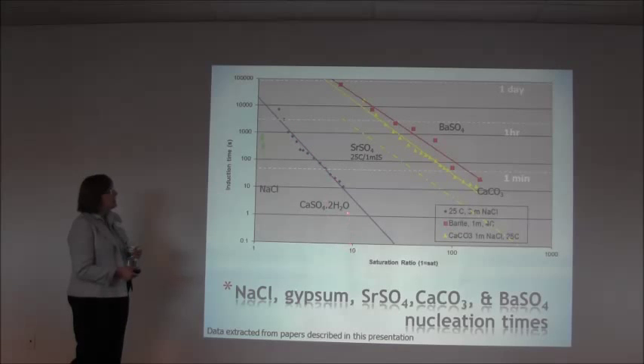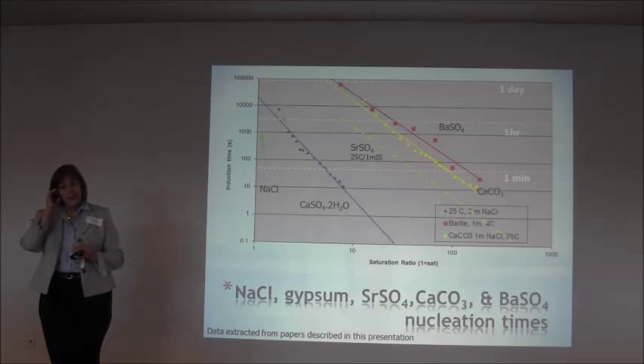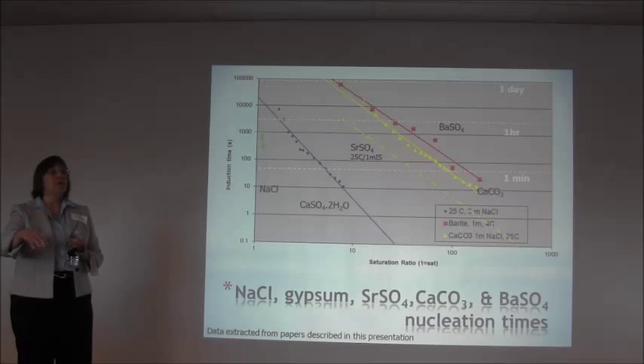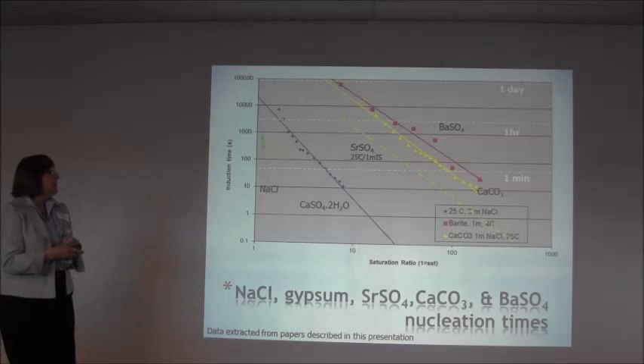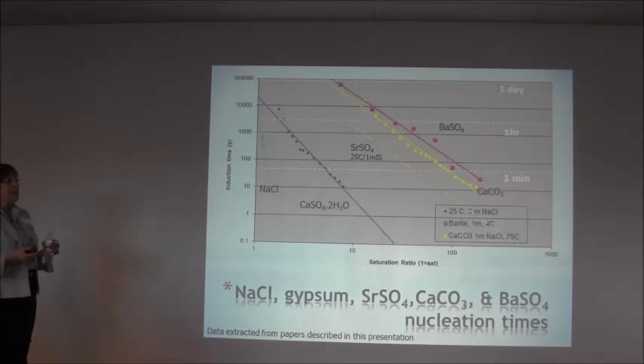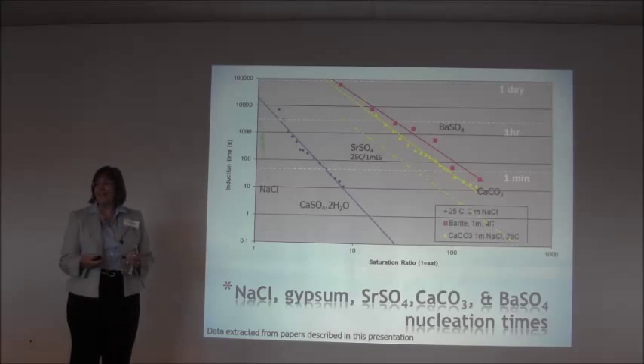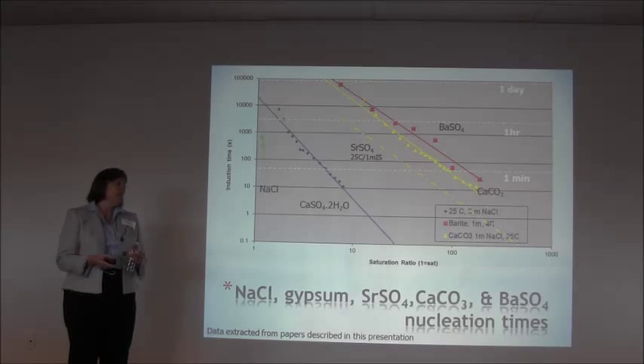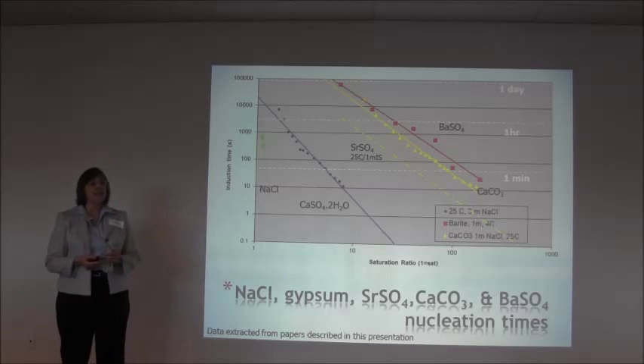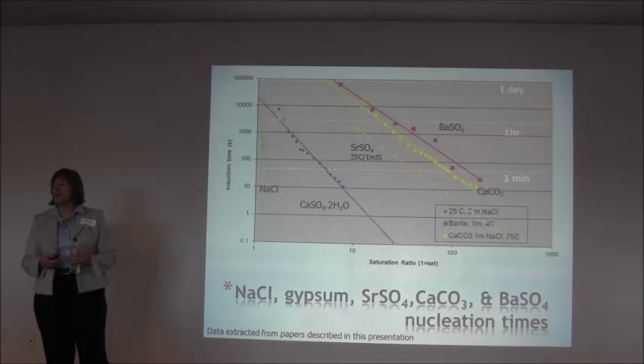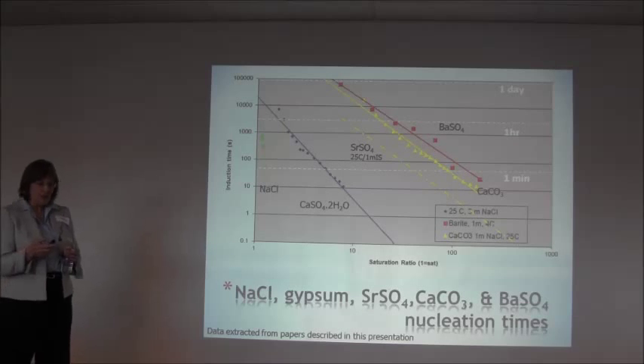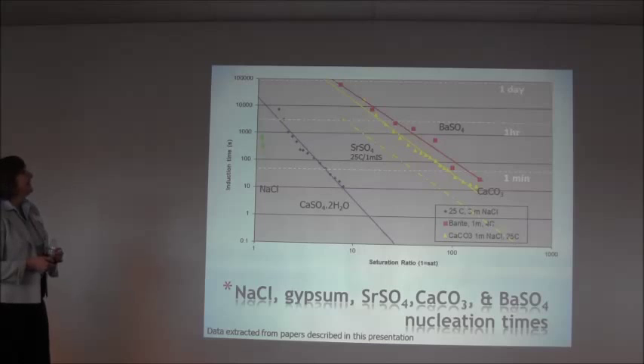So that means that your scale tendency on gypsum, for example, can be much higher. It can be up at 10 if your induction time, the time in seconds, is only going to be 10 seconds. What that means is if you have something flowing really quickly, it's not going to have time to nucleate and adhere. So even though we're worried only about the thermodynamic driving force, you can see that there's different ways that you can calculate. Okay, even though the program said the scaling tendency is 4, is that a problem? Well, no, it's not going to be a problem. It depends on how fast it's flowing or how stagnant it is. It depends on a lot of things. So what we're going to tell you is 4, and then you're going to figure out, okay, is that important?